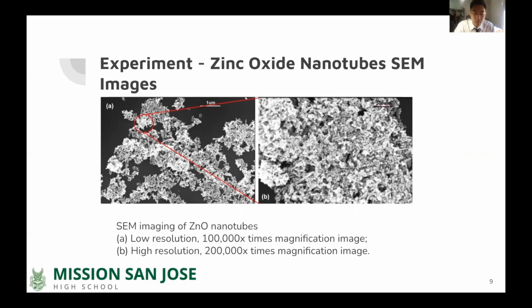Their length and thickness are both controlled by the pH of the liquid used. Strong bases with higher pH values cause the nanotubes to be longer and have thinner walls. Conversely, stronger acids with lower pH will cause the tubes to be shorter and have thicker walls. The time the mixture stays in the chamber also plays a role in its shape. The density of nanotubes on average will increase with time inside the chamber. The ideal conditions have to be determined experimentally.